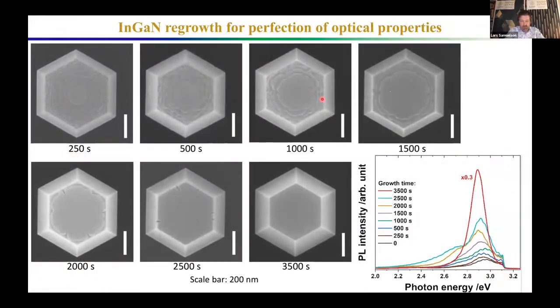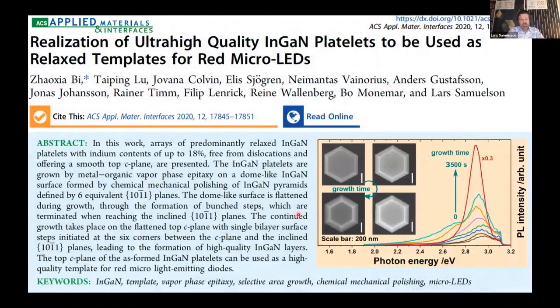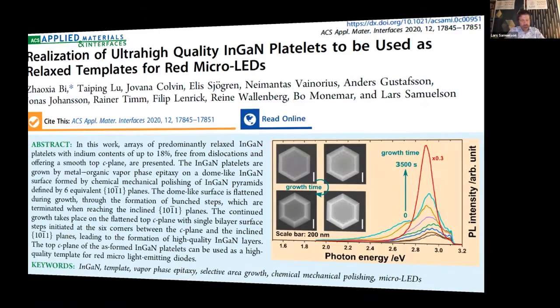But that was again a developed technology. You can see how these multi-step features disappear one by one. And when he's finished with this, he has actually, as seen by scanning probe, an atomically flat surface that you can use for your devices. This was published in 2020, in the difficult year of 2020: realization of ultra-high quality InGaN platelets to be used as relaxed templates for red micro-LEDs.